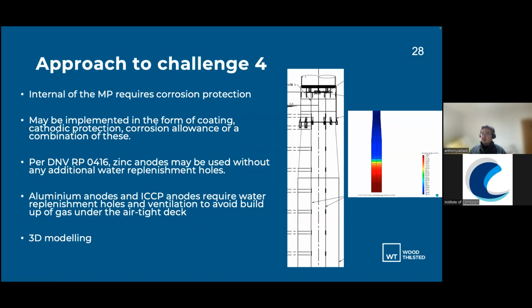So currently, the industry is looking at providing both coating and cathodic protection, sometimes both, sometimes one of them. But here we're looking at coating and using galvanic anodes. In this case, we use zinc because the amount of hydrogen is a bit less. And as per DNV RP 0416, we are looking at that without any water replenishment holes, because then the amount of hydrogen that zinc produces in the reaction does not currently affect the pH internally of the water.